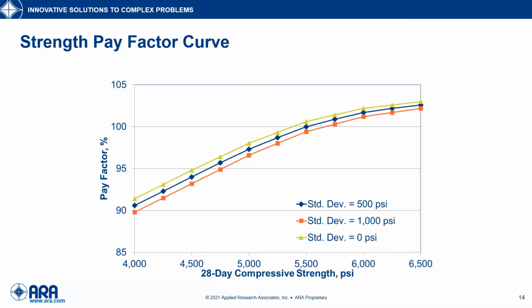And linear interpolation was used for strengths and standard deviations that do not fall on these curves. But as you can see here, the target was standard deviation of 500 psi and 5,500 28-day compressive strength. And then if they increase the strength, that was an incentive. Decreasing was seen as a disincentive. And then as you reduce your standard deviation, that's also seen as being beneficial. So on all these factors, we had these curves with the pay factor on the y-axis and on the x-axis, the characteristic we were looking at.